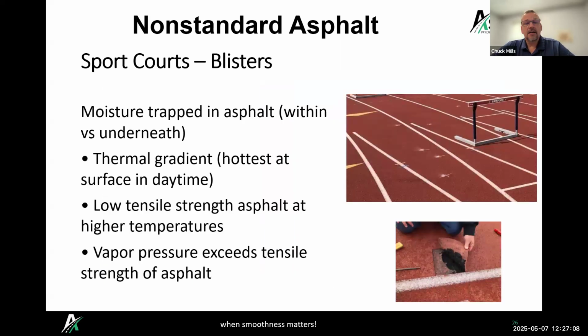Another thing that we can see are blisters. And so this is where the coating kind of blisters up after being in place for a while. And how does this happen? It's usually moisture trapped in the asphalt, either within the asphalt or underneath the asphalt. And then the thermal gradient, it's hotter on a sunny day and things like that. So that water wants to kind of expand up, and the vapor pressure in there exceeds the tensile strength of that surface of the asphalt and causes that coating to blister up. So that can be an issue.